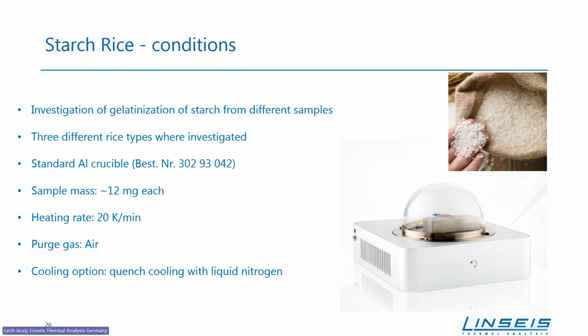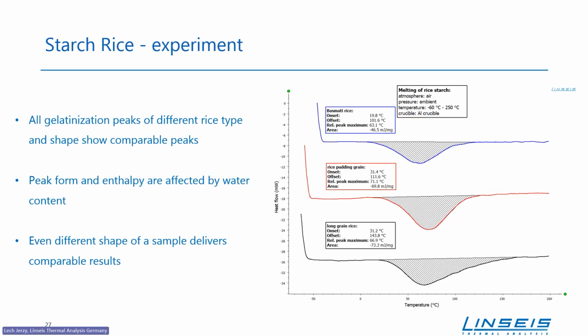Another application is rice, investigation of gelatinization of starch from different samples. We use 3 different rice types to be analyzed in aluminum crucibles, 12 milligram sample mass each, and heating rate 20 Kelvin per minute in air atmosphere. We also started from sub-ambient temperatures. What we see is that all gelatinization peaks are different, depending on the rice type. We were able to measure the enthalpy of change, as you can see, and we also see different shapes for different samples.